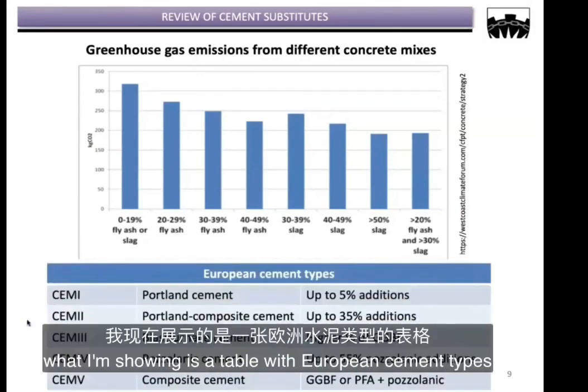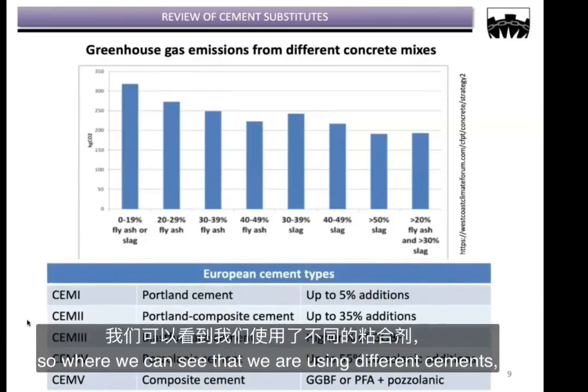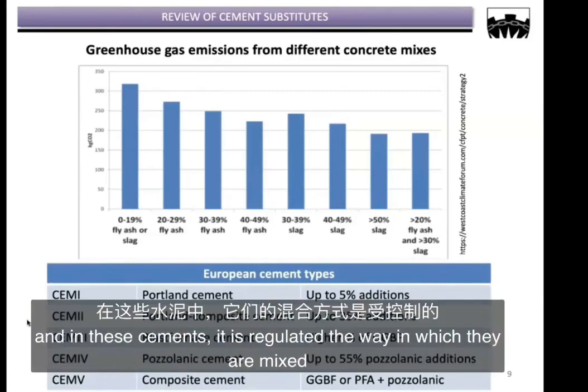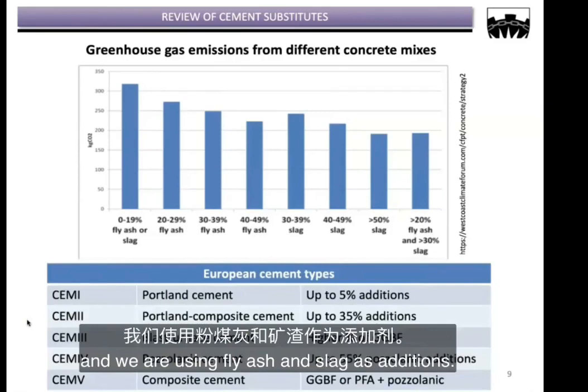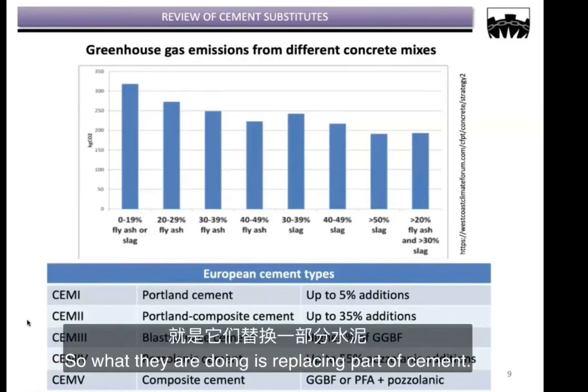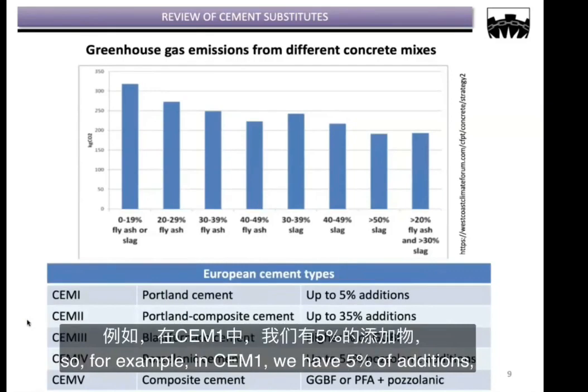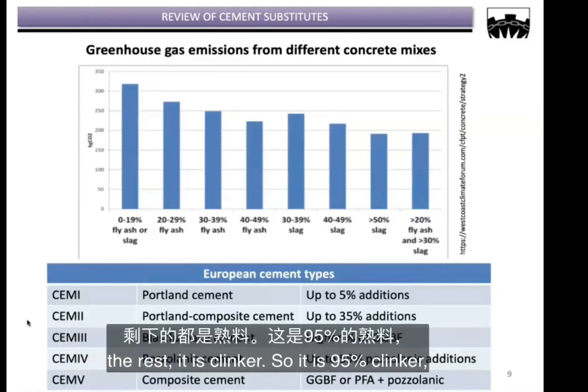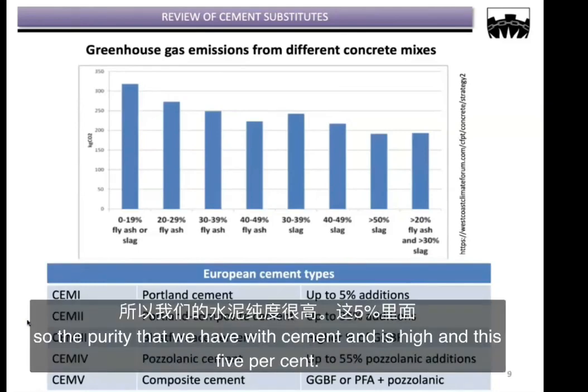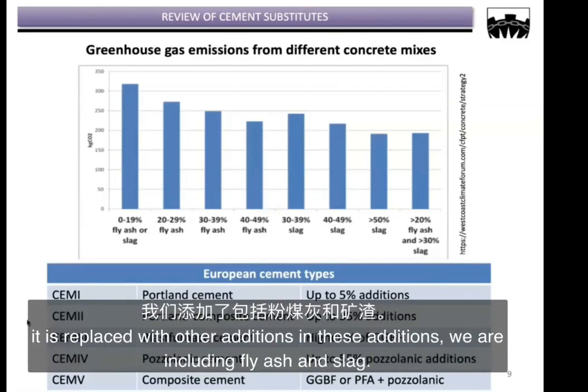Here, for example, I am showing a table with the European cement types. We can see that we are using different cements, and in these cements it is regulated the way in which they are mixed, and we are using fly ash and slag as additions. So what they are doing is replacing part of the cement. For example, in CEM1, we have 5% of additions. The rest is clinker, so it is 95% clinker. So the purity that we have with cement is high, and this 5% is replaced with other additions. In these additions, we are including fly ash and slag.